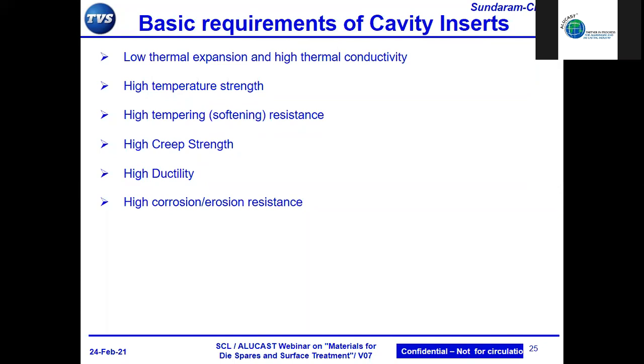What I was trying to say in my presentation earlier is that the liquid metal we are using today has an iron content of almost around 1%. And this 1% iron content is actually intentionally added into the liquid metal to avoid this kind of soldering phenomenon.